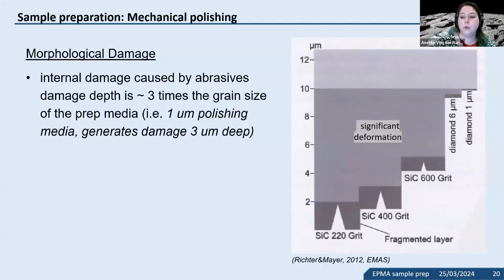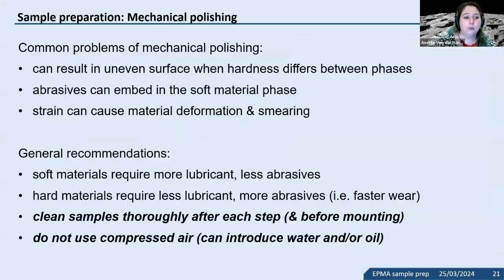Then an important thing that I've seen in data can be a problem: if you put too much pressure on your sample, you can really produce a certain amount of damage in the material. And so what this shows is the depth of this damage. So oftentimes going from one polishing step to the next one, you still want to remove a good amount of material to get to the undamaged part again. And this is what this is supposed to show.